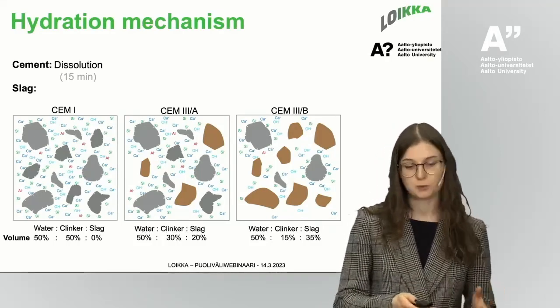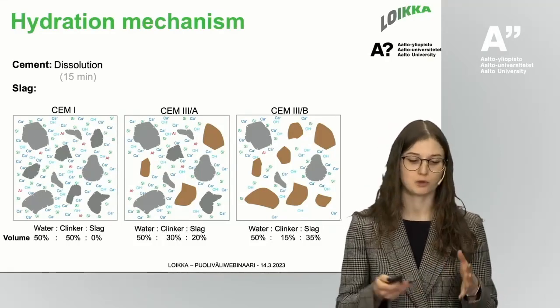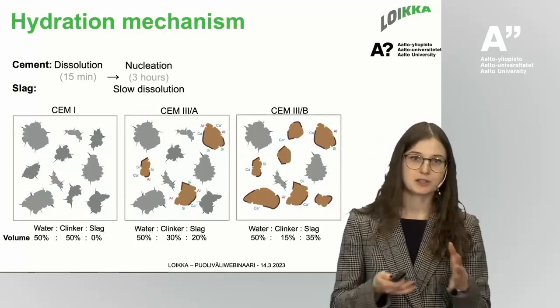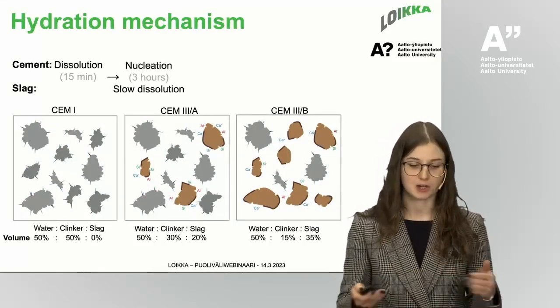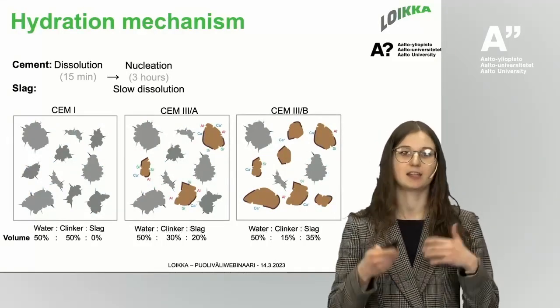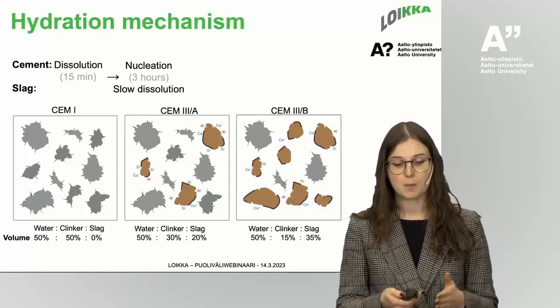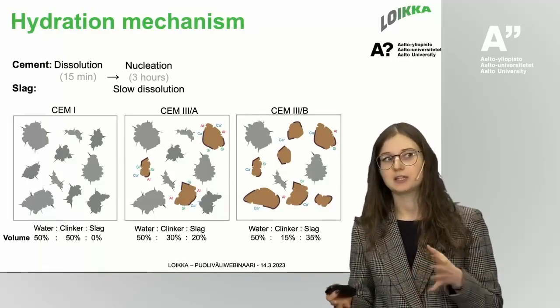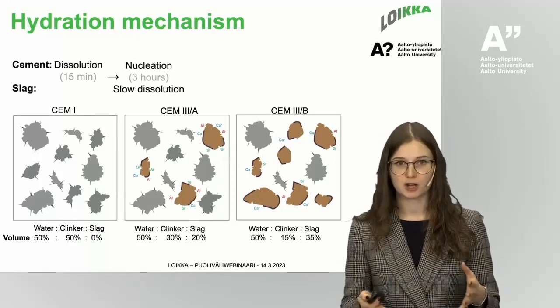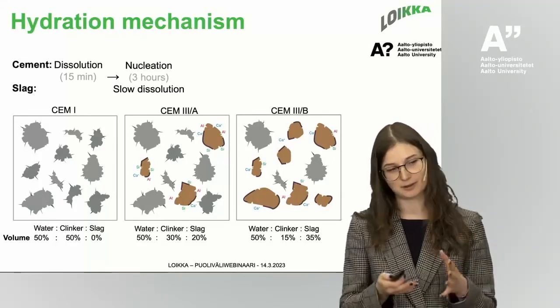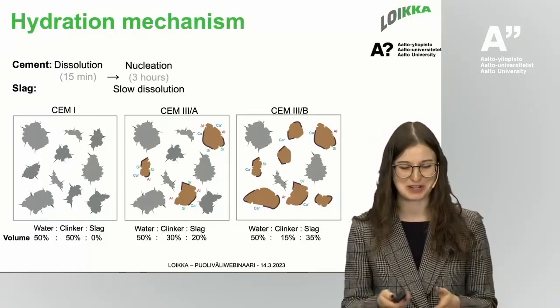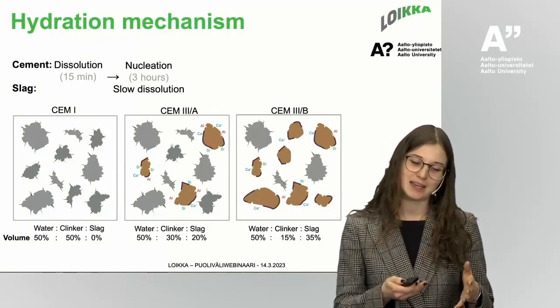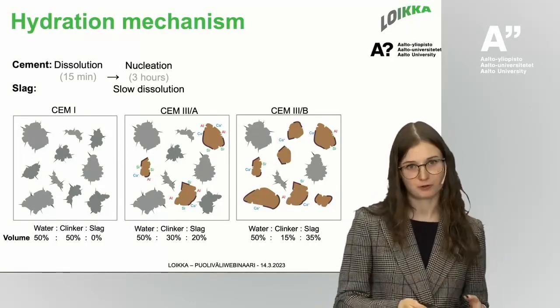So at the moment, when we start forming the hydrates on the clinker grains, there are some spare ions that can actually attack the slag and help it to dissolve. But since the slag has a bit different construction of its crystalline structure, the way it behaves further is a bit different from the clinker grains.